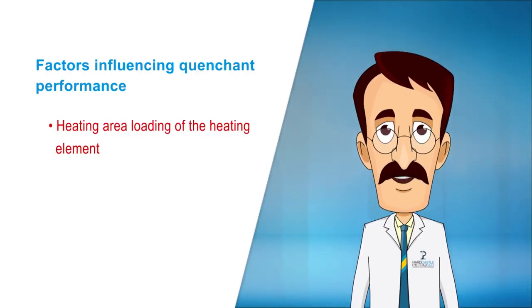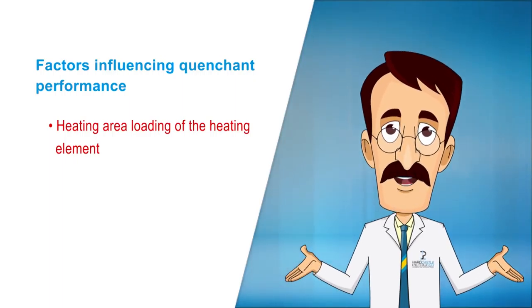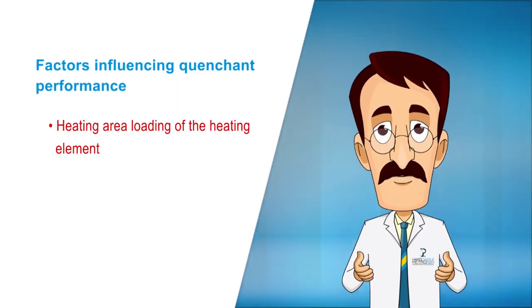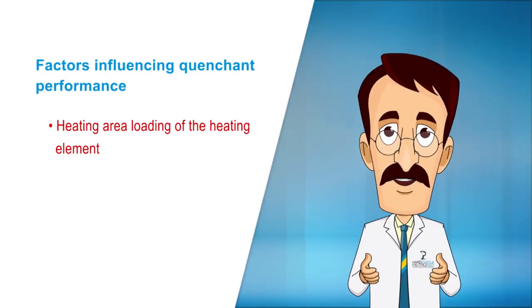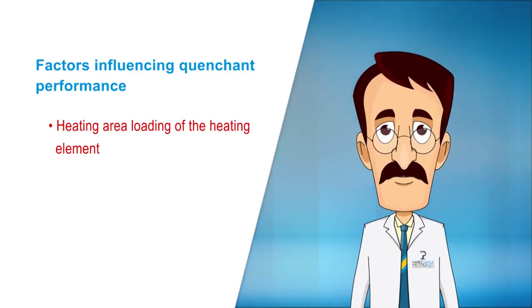The heating area loading of the heating elements should be limited to about 1 Watt per centimeter square. If a higher loading is used, good movement of oil in the area of the elements must be maintained to avoid overheating.